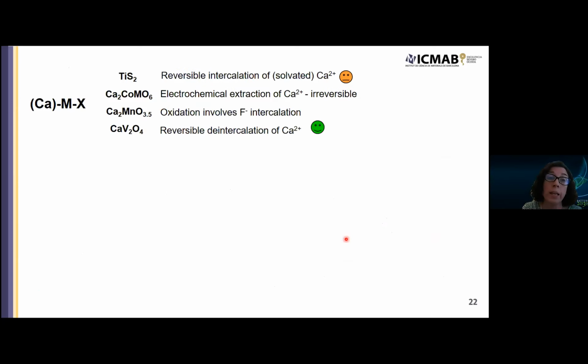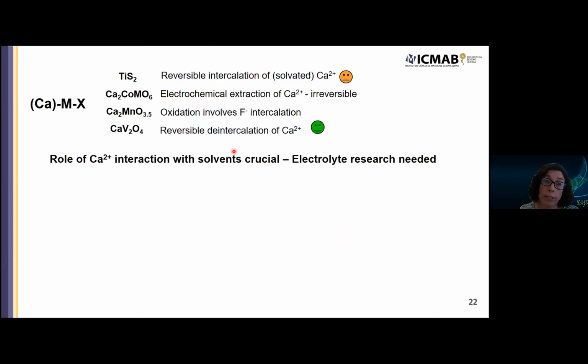So to sum up a little bit, we were studying positive electrode materials, and we saw all types of behaviors: reversible intercalation of calcium, but together with solvent molecule for TiS2, some irreversible behavior, some electrochemical oxidation, in some cases involving extraction of calcium, in others involving intercalation of fluorine, but irreversible, but also for the case of the vanadium compound, the behavior seems to be reversible. So at this point, I think that the role of the calcium interaction with solvent is crucial, and there is the need for more electrolyte research for sure.